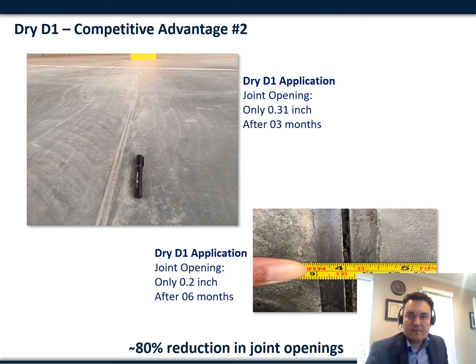The second advantage is that DRY D1 is excellent to control joint spacing. When compensating the shrinkage, you have wonderful results on joint openings. For example, on this project you have a joint opening of only 0.31 inch after 3 months. On this one, we have 0.2 inch after 6 months. We calculate about 80% reduction in joint openings on your project.